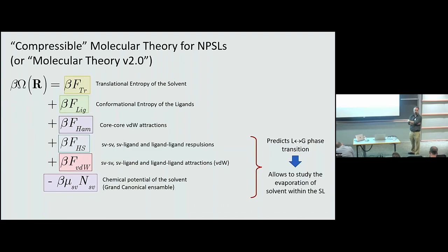We don't have the incompressibility constraint anymore, but we added some terms that now explicitly describe the interactions between the solvent molecules and between the solvent and the ligands. So we added the term for the repulsions. This is just using some hard sphere functional. And then the van der Waals interaction, the attractive branch of the Lennard-Jones interactions,